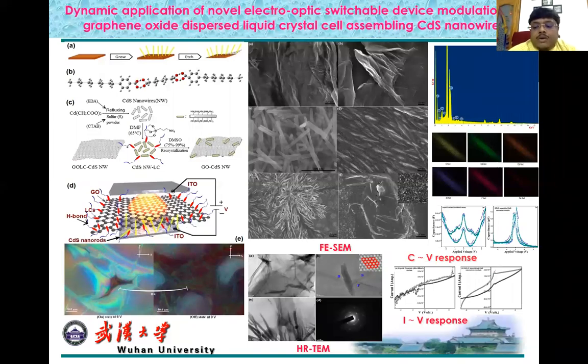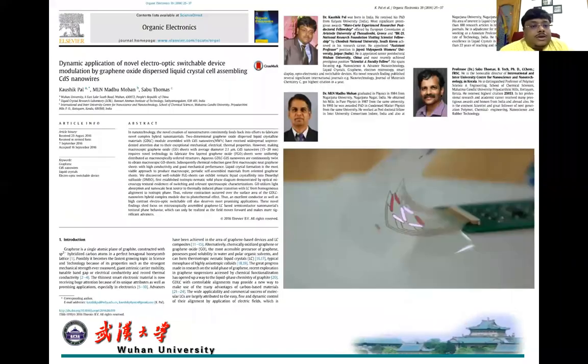Those hybrid compound samples we sandwiched inside the cell, and we can observe the same electro-optical switching. You can see, and we also did the characterization of CV and IV. You can see the hysteresis peak coming, and several cyclic patterns coming from the hysteresis loop of the CV responses. This work is published in Organic Electronics.